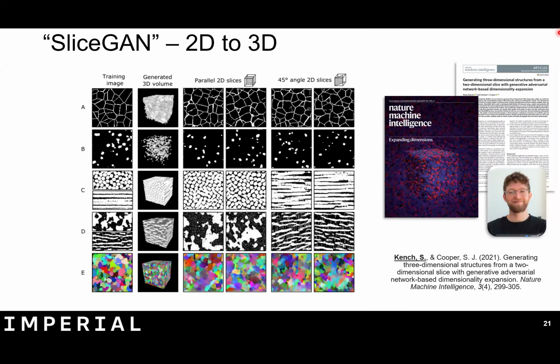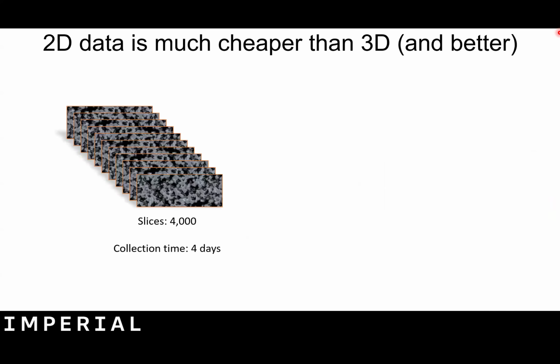About a year or two after that, Steve Kench joined my group and worked out a method for generating 3D microstructural volumes from 2D data. And so this means if you assume that your data is isotropic, the same in every direction, you can pass it a single 2D image, and it will then generate for you 3D volumes, which is a very useful thing because 3D imaging at the microscale is very slow. So basically, X-ray computed tomography is not able to image battery electrode microstructure. It can't see the difference between the carbon binder domain and the pore. And so you end up with active material particles floating in a sort of fuzzy free space, which is not good enough to understand the relationship between structure and performance.